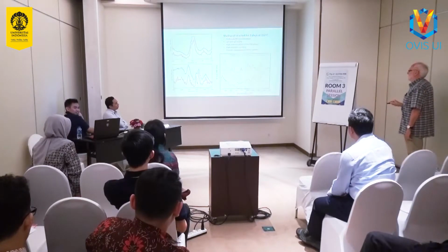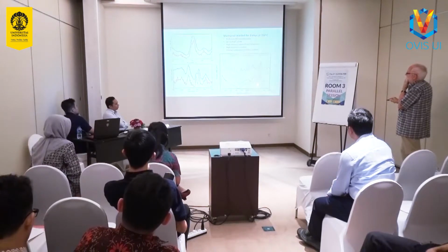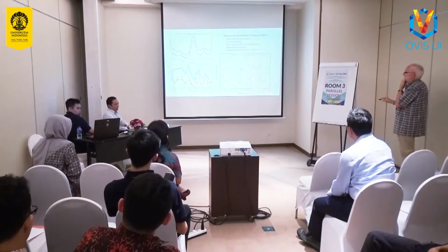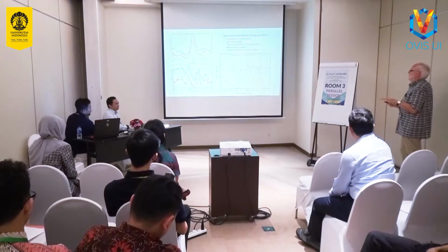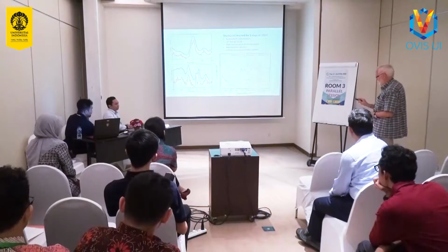We run a number of model compounds to compare the spectra we see in the zeolite with model compounds to try and deduce what species are there. The bottom spectrum here was actually obtained by putting dimethyl ether into the zeolite rather than methanol, but it's very similar to what we see with methanol. And the model compounds here were durene and orthoxylene, and the closest comparison we have is with orthoxylene. Not identical. What we actually have, of course, in the zeolite is a mixture of molecules, but on average they look like orthoxylene. So methyl substituted aromatics. No particular surprise there, but this is the first time this had been done with a working catalyst, an industrial catalyst. And only neutrons could do that.